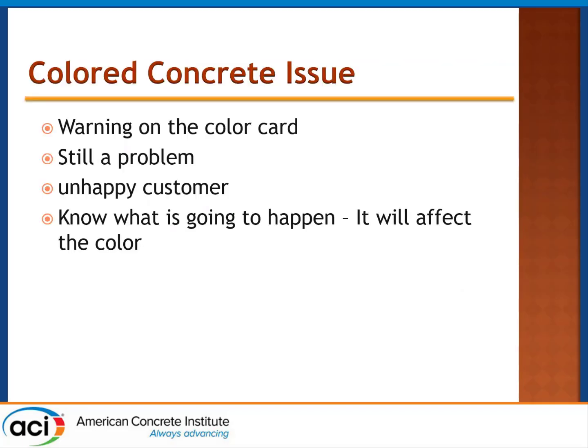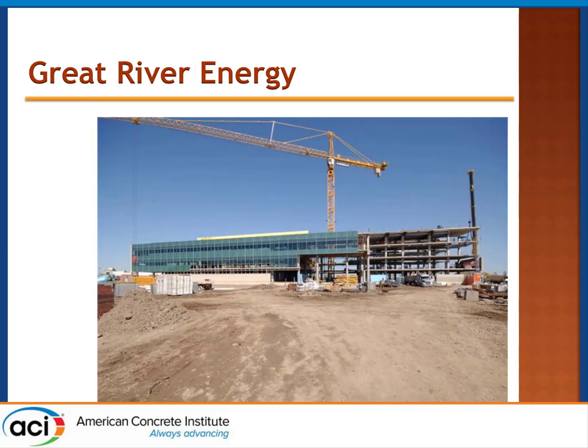So we had a warning on the color card that said it's going to be dependent on the base color of the concrete. It affected the color massively. And what was the problem with those colors as we went to high volume fly ash in interior concrete mixes? That they wouldn't like the color, and so what would we do? We would tear it out and do it again. So no matter how much clinker we didn't use the first time, we ended up using a lot more by doing it the second time. Plus, everybody wanted that. But that's not really why we're here.